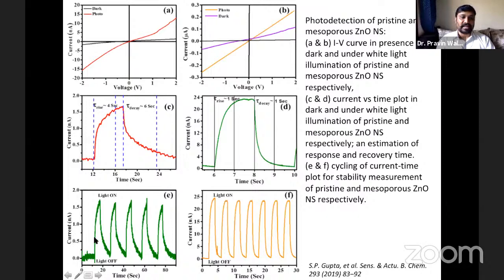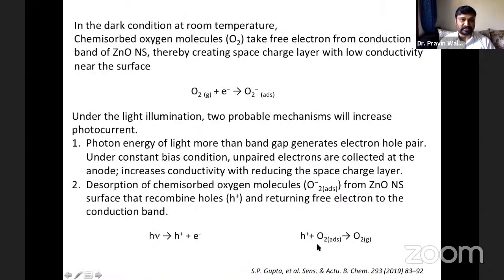And here you see the light on and off. If you switch this light on and off, you will find this is the responsivity. And as compared to this pristine, you can find this annealed sample has a very good number of cycles, and stability is quite good in this sense, right? So what is the advantage of doing all these things, right? See, in the dark condition at room temperature, what happens? Your chemisorbed oxygen molecules can take a free electron from the conduction band of the zinc oxide nanostructures, nanosheets, and can create a space charge layer with a low conductivity near the surface. And here this reaction happens. You have the atmospheric oxygen, and you adsorb oxygen, and you take the electrons from the zinc oxide, and you can find this adsorbed oxygen species.